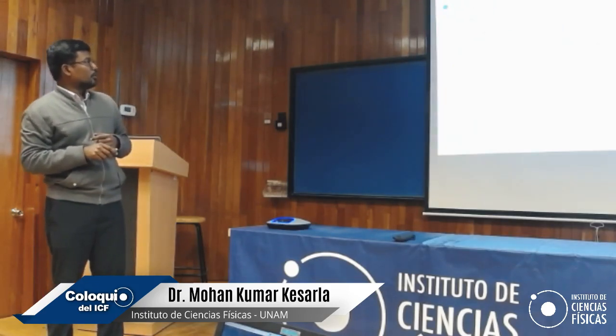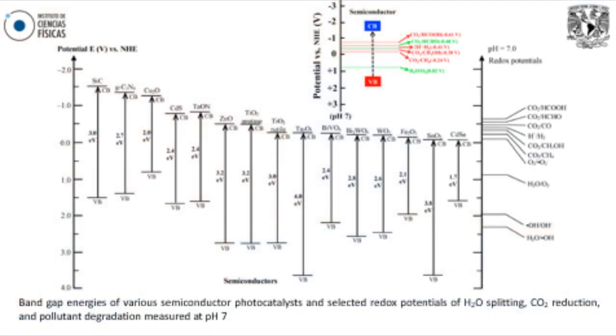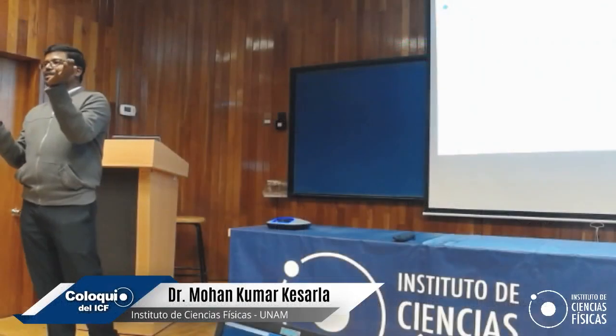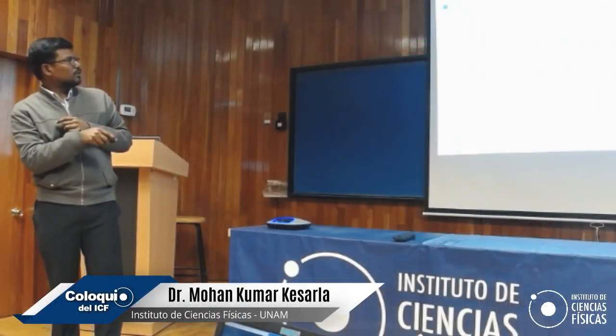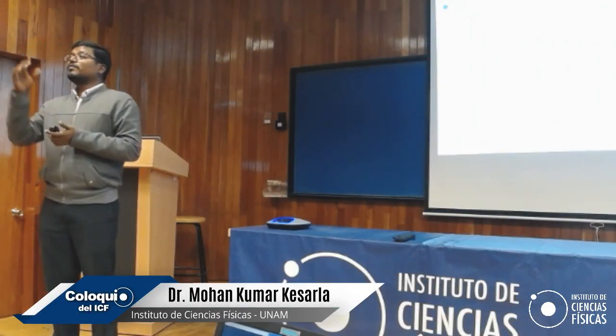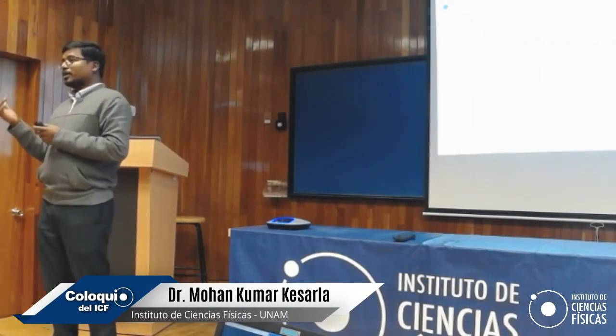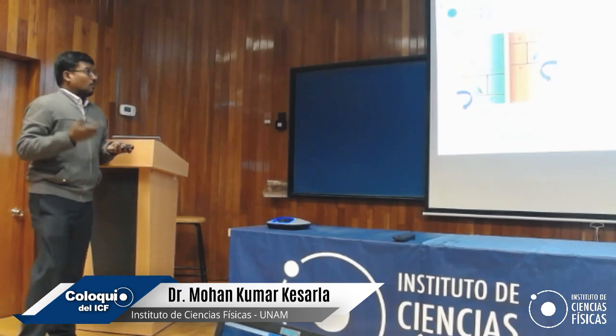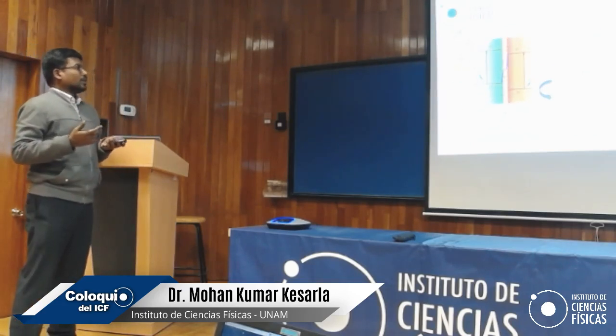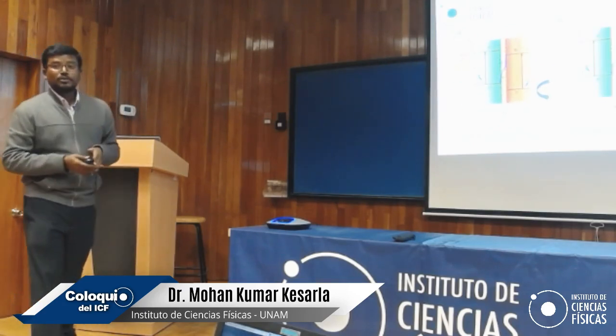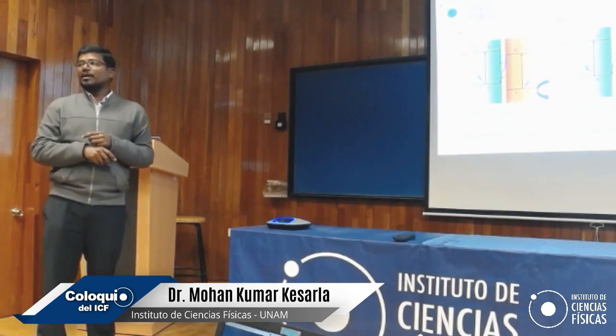For example, if I am going to make a heterojunction with g-C3N4 and WO3, this WO3 has a conduction band potential around 0.4, and for hydrogen production I need minus 0.7. If I am doing this type of heterojunction, the charge transfer from the highest conduction band to the lowest conduction band will occur, and it will minimize the opportunities of reduction. So what next? Even type 2 is not working in some cases, so people started reducing just in heterojunctions.